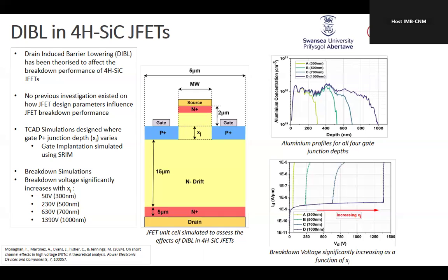So two things with JFETs are this drain-induced barrier lowering, I'll cover that in the next slide, and this kind of threshold voltage instability of devices across an 8-inch wafer or a 6-inch wafer in silicon carbide. And if you look at the data sheet from Qorvo for a device like this, they specify the threshold voltage. There's a big range, right, for the threshold voltage, and that's the reason for that.